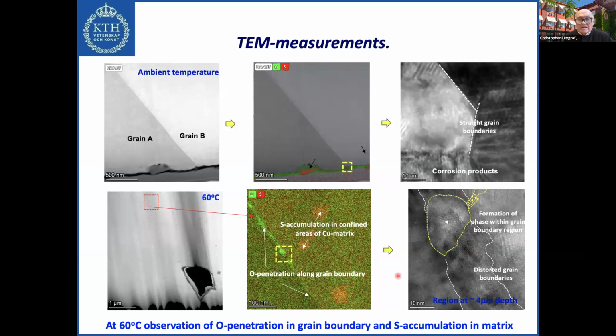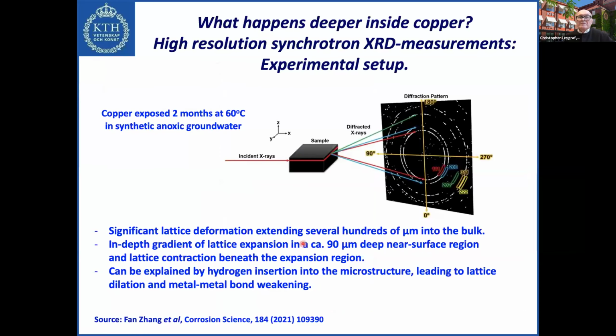And as it looks, sulfur is not seen as much here, but it's seen inside. So sulfur probably comes after oxygen because of the much higher defect regions. And then it clusters into areas, confined areas, where you see the sulfur inside the grains and far in the material. So the question is, how deep can this go? So what happens deeper inside the copper?